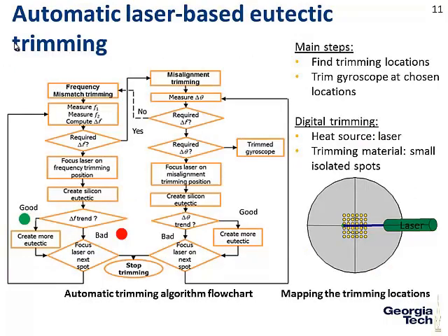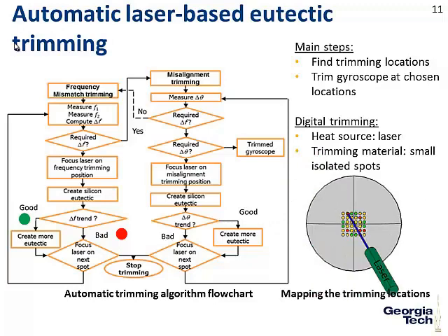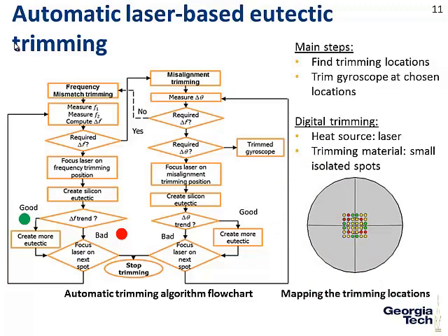Those locations are really great because it's really easy to find them. The only problem is when you have a gyroscope, you don't see them. So you need to find them. There are different ways, but one easy way is just to have your laser go around your device and scan, trying not to melt too much, just trying to get your result and pattern. So this is a simple animation to show you that you can find easily your good spots and also your bad spots, and then you remember them, and then you come in a second scan and you only go to the locations where the frequency split actually went down, was reduced, and you put more energy, more power to get the most effect.